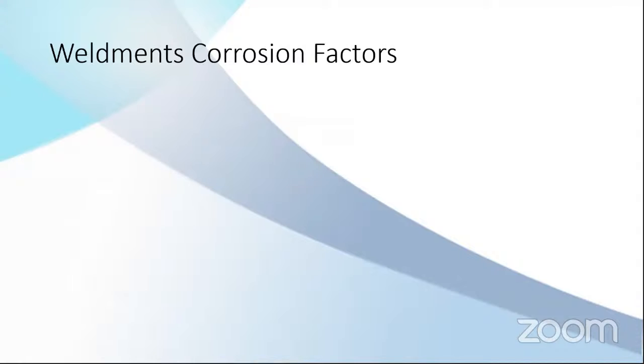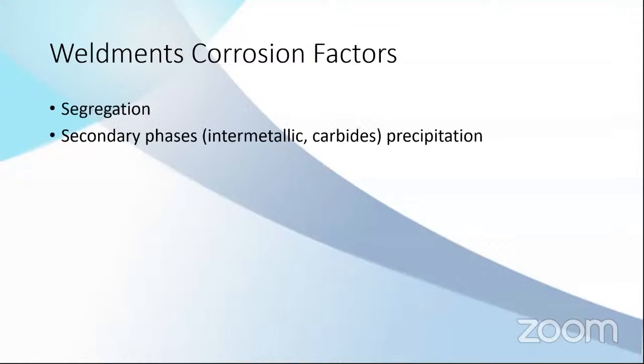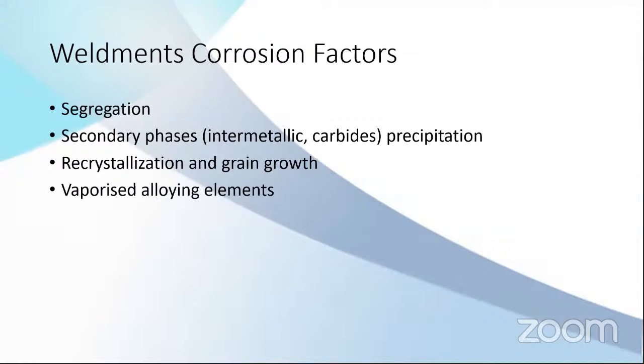And what makes welds susceptible to corrosion is the segregation of the chemical elements. There's the probability of secondary phase precipitation. There's the possible heat affected zone. The grains have recrystallization, also probably grow, and also vaporized alloying elements. When the parent metals get heated, some of the chemical elements get vaporized because of temperatures that reach thousands of Celsius.